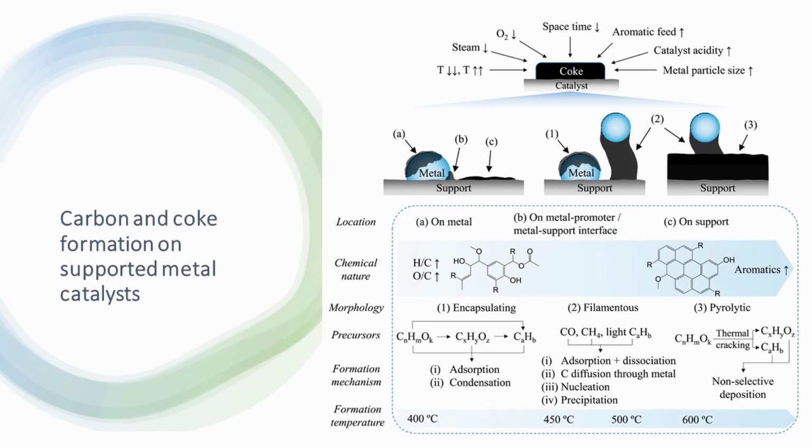Carbon is typically a product of CO disproportionation, while coke is produced by decomposition or condensation of hydrocarbons on a catalyst surface and typically consists of polymerized heavy hydrocarbons. Nevertheless, coke forms may vary from high molecular weight hydrocarbons to primary carbons such as graphite, depending upon the conditions under which the coke was formed and aged.